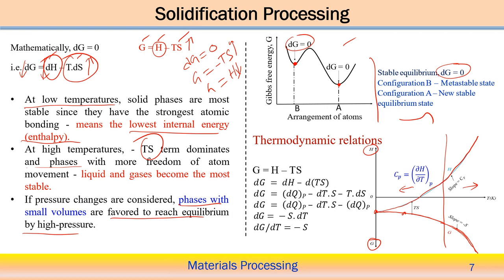So mathematically you can see that G equals H minus TS, enthalpy minus temperature times entropy. So dG equals dH minus d(TS). In this case dH is equal to dQ at constant pressure, as we have already seen. Now d(TS) is dT into S plus T into dS. We have seen that at equilibrium condition dS equals dQ by T, so T into dS is basically dQ. So T dS equals dQ at constant pressure, and these are balanced. So dG equals minus S dT. So dG by dT equals minus S, all at constant pressure.